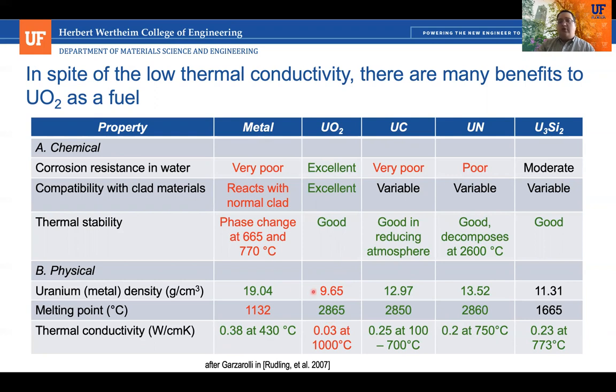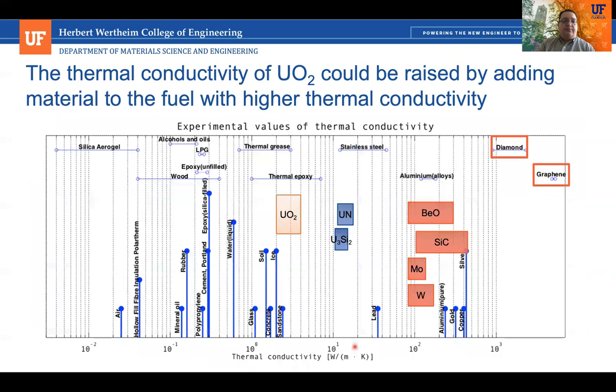But the problem is related to efficiency. It has a low uranium density and this low thermal conductivity. So we want to be able to maintain all of these benefits of UO2, but also increase the efficiency. An approach that a number of different researchers have attempted is to take uranium dioxide, but then mix in other materials to create essentially a composite fuel, trying to raise the overall thermal conductivity of the material. And people have tried to mix in lots of different materials, including diamond and graphene, beryllium oxide, silicon carbide, metals like molybdenum or tungsten, or even other fuel materials like uranium nitride or uranium silicide.